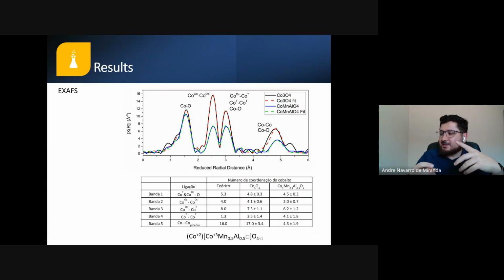And when we call them defects, it's good for the material, because when we have oxygen vacancies in this material, we have a really high energy surface. When we have a high energy surface, we can mediate the formation and the decomposition of the lithium peroxide with this catalyst. We also have some decrease here in the cobalt-cobalt bond. This is because we have different materials in this catalyst, such as manganese and aluminum, but we also have some defects in the cationic areas.